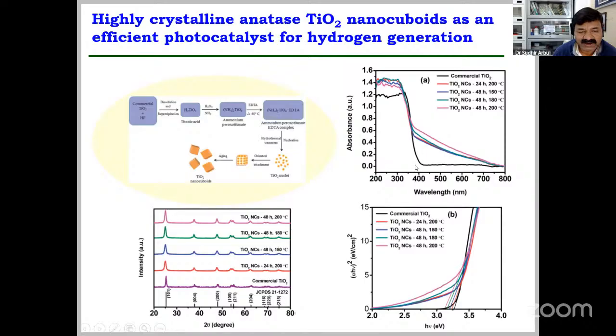So here we tried to identify why this absorption behavior is different in this case. We found that in this case, some nitrogen is getting doped in TiO2 at the oxygen place. Due to that, we are getting this enhanced absorbance in this region due to the formation of TiO2 minus x N x. Okay, so using this, we are getting a change in the band gap of TiO2.